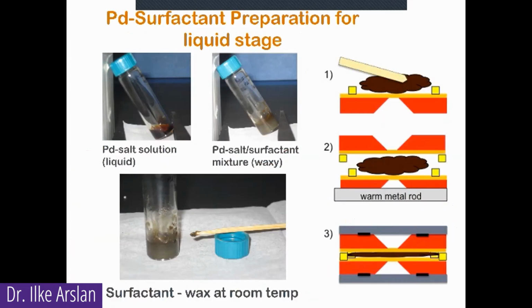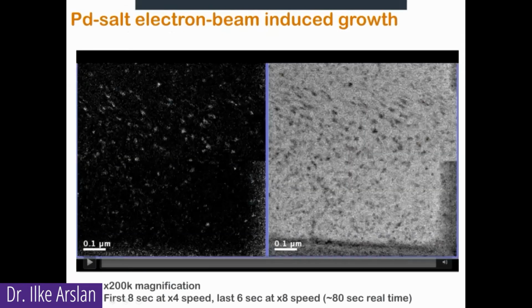And what we wanted to do was continue on with this work that I had started at Sandia, which is the palladium pores. We want to understand how they synthesize so that we can understand how to synthesize them better. So we wanted to grow them. We wanted to synthesize them in situ. So we're looking at a palladium salt solution and the surfactant, which is what creates the pores. So this is both in STEM. It's a dark field, bright field pair.